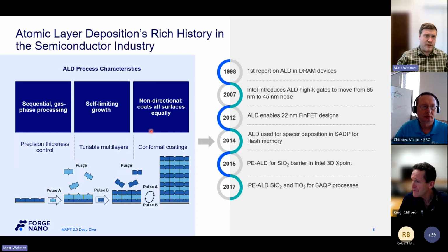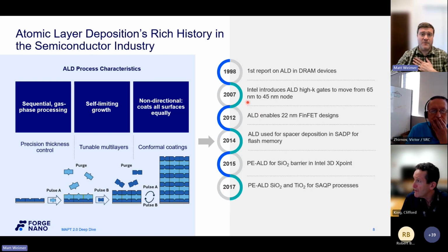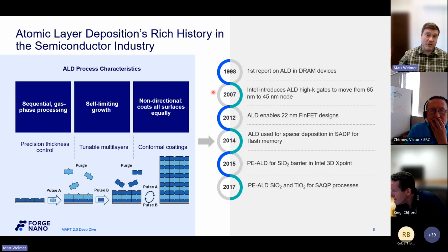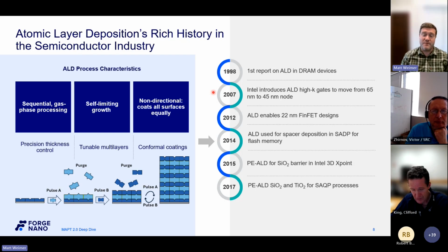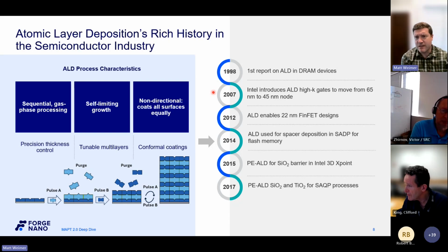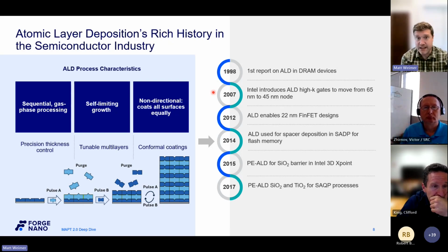Okay, so if we start on the right here, I usually talk to a lot of people about ALD. Not everybody has a background in it, but in the 300 millimeter space, ALD has been around for quite a while. So here's a bit of a timeline of how it's been used. For my money, the most important thing here was in 2007 when Intel announced to the world, hey, ALD is good enough as a high volume manufacturing production technique to be used in our high-k metal gate dielectrics when they went from the 65 to 45 nanometer node. I think those numbers are correct. I'm not a historian. I was a bit young back then, so if those are not exactly correct, I apologize. But the point is, this announced to the world that ALD is a high volume manufacturing technique. I'm sure you all remember at that time, Intel was the standard for consistent manufacturing. So from an ALD history perspective, that was quite a high watermark.